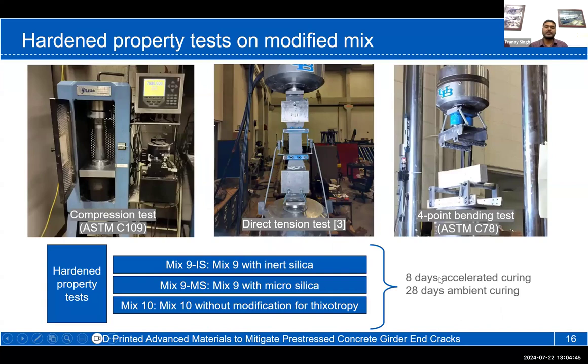So eventually, after this rheological optimization, we obtained 3 mixes that were printable, and they had fibers in them. They started from our base SSCC mix. Now we tested these 3 selected mixes for their hardened properties. The mixes were mix 9 with inert silica, mix 9 with micro silica, and mix 10 without any additional ingredients. We tested them at 28 days of ambient curing.